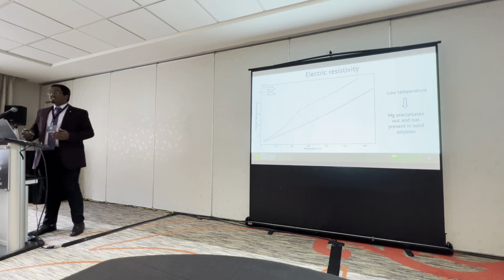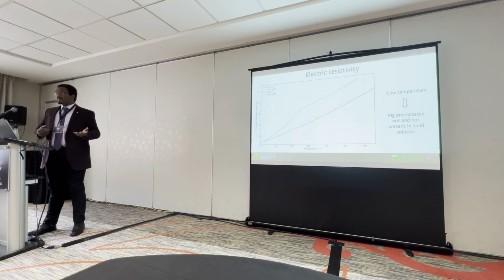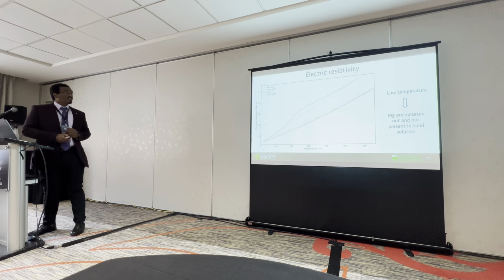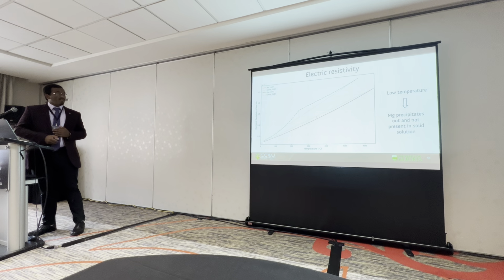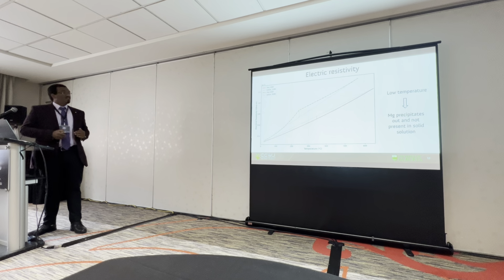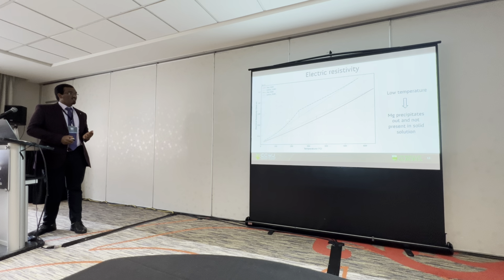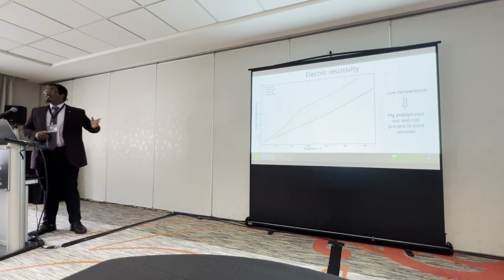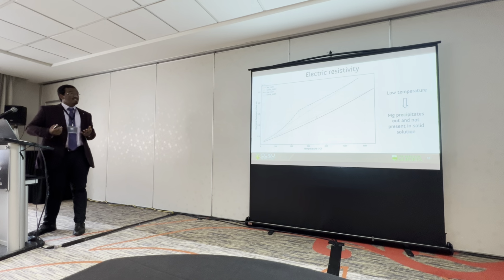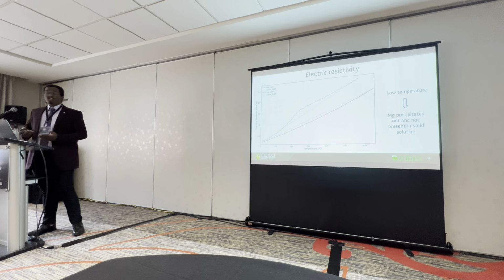And as expected, the alloy 5183, which has magnesium, tends to have a higher electrical resistivity, shown by the green dotted lines. And 1100, which is just pure aluminum, tends to have a very similar electrical resistivity across increasing temperature. But we found that the electrical resistivity of 5183 tends to come closer to 1100 at lower temperatures. This was based on the fact that magnesium precipitates out and is not present in the solid solution anymore, thus having a similar electrical resistivity to that of a pure aluminum alloy.